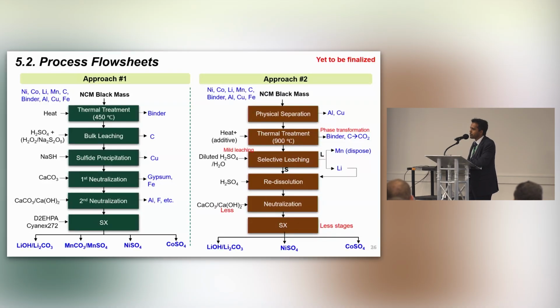Actually, we are developing some process flow sheets targeting different approaches. The first approach is NCM black mass processing, targeting bulk leaching and removing the binders and graphite upstream. And our final target is making lithium as lithium carbonate, and manganese, nickel, and cobalt as sulfates, having a purity of more than 99.9%, which is suited for battery materials. And this is something we are developing based on our industrial experience.